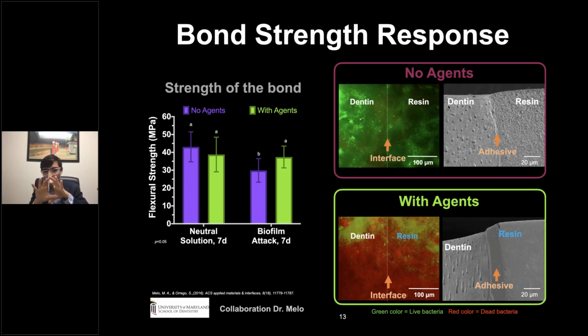Then we tested 2 environments. The first for 7 days was a neutral solution with no bacteria, just as a control. The second media we used was the biofilm, samples exposed to this culture of bacteria, which was able to produce esterase activity and acid activity and so forth. The 2 samples we prepared: one with no antibacterial agents or acid neutralization agents, which is the purple group, and the green group is with the antibacterial and acid neutralization agents.